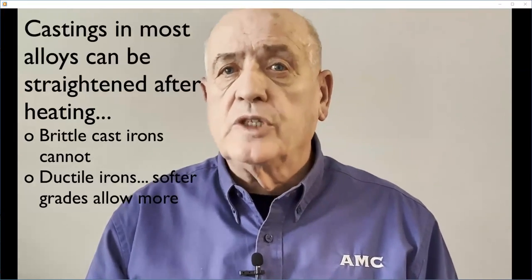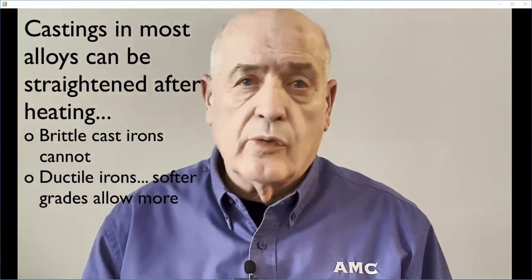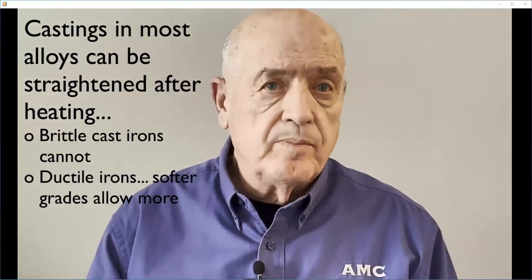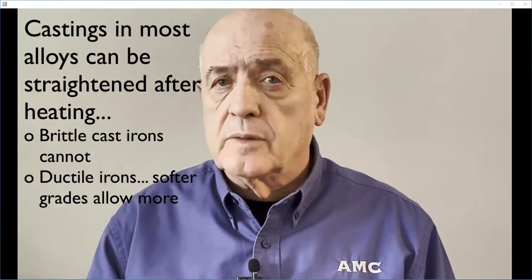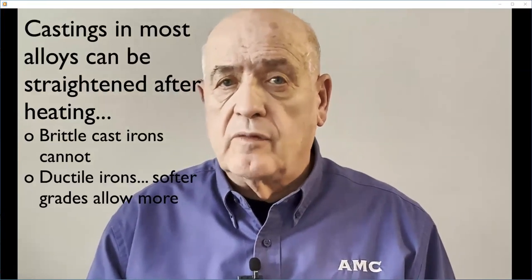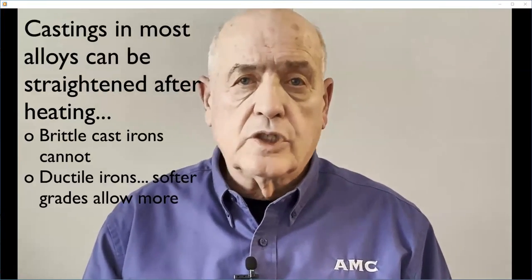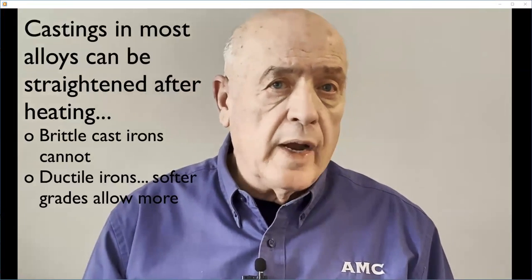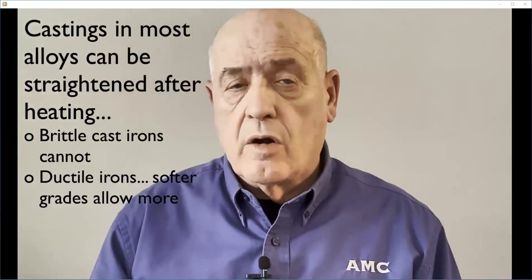compromised. The consequence of accidental casting distortion from removing the casting from the mold too soon while the casting is too hot and too soft depends on the alloy. Most casting alloys can be straightened, although brittle cast irons cannot, even if heated to high temperature. Ductile irons can be straightened in varying degrees depending on the strength grade. Softer grades can be straightened more than the harder ones.